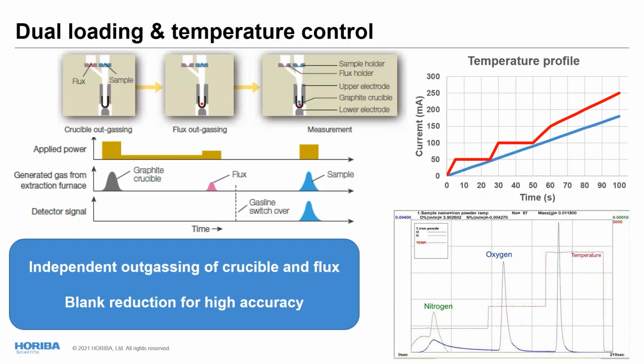For example, you can see in this example 3 different steps of temperature that helped us to differentiate 3 different forms of oxygen. Typically, the first one will be the contamination, what will be on the outside of the sample or the surface of the sample. But the 2 other peaks may be related to different forms of oxides in the sample.